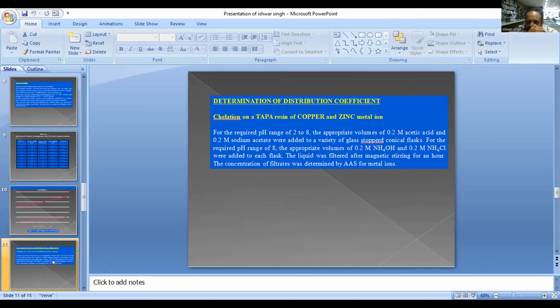And chelation of tapa resin of copper and zinc, as I told earlier, this resin is very effective for the removal of copper and zinc. The efficiency is 83% and 80% respectively, as I discussed earlier. For the required pH of 2 to 8, an appropriate volume of 0.2 molar acetic acid and sodium acetate was taken in glass stopper conical flasks. The liquid was filtered after the magnetic stirrer, and the concentration was taken by AAS. So it is found that the most chelation by the tapa resin is for the copper and zinc metals respectively. Both are heavy metals.